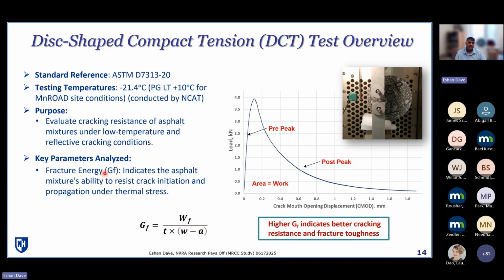Again, the purpose here is to look at how the cracking resistance changes at low temperatures under reflective cracking conditions. Now, as with other tests, right now there are ongoing efforts to also look at additional parameters that we can get from this test beyond the energy. Again, that's an ongoing effort under development. So for this presentation, I've limited it to presenting just fracture energy for this semi-circular bend or compact tension test, but please be mindful that in the future, once those other parallel efforts have matured and we have other indices, we may have additional indices that may be presented for this test as well.